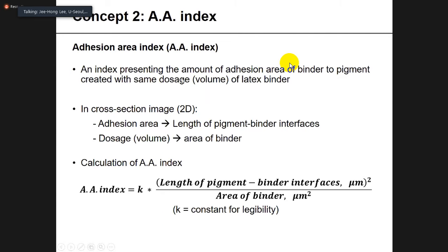Introducing the second concept, named the adhesion area index, which is also abbreviated as AA index. This is an index presenting the amount of actual adhesion area of binder to pigment particles created with the same dosage of latex binder. If you also put this into a cross-sectional 2D image situation, the adhesion area of binder would correspond to the length of pigment-binder interfaces, and the dosage would be the area of binder. So the calculation is the square of the length of pigment-binder interfaces divided by the area of binder. Also, the K is just for the legibility of the index.